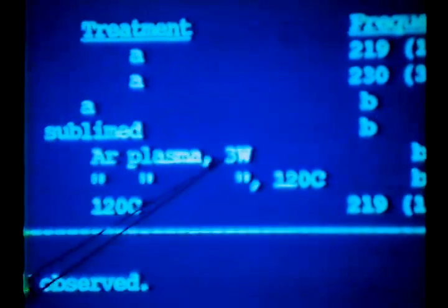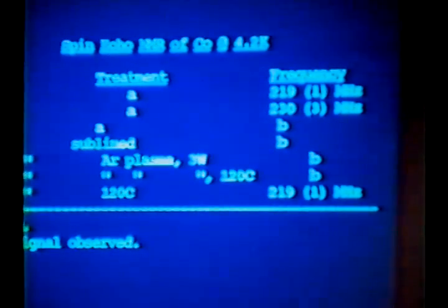But what happens if you put in cobalt carbonyl and run that? You don't get any signal. Dicobalt carbonyl in the zeolite that's been sublimed in there, there isn't any signal observed. If you treat this material in the plasma at 3 watts, you don't see any signal. But remember, in ferromagnetic resonance, the data I showed you right here, there's a signal there for cobalt metal particles. We know they're metal particles. We know they're small. We know they're superparamagnetic. That suggests the particles are on the order of 5 angstroms, because these are all done in liquid helium, and the critical particle size is 5 angstroms. Very small metal particles, highly dispersed.